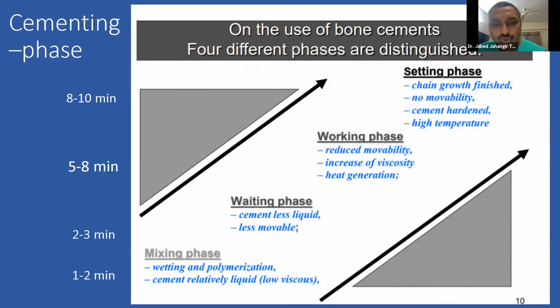We all know it is 4 phases. Mixing phase lasts for 1 to 2 minutes, and waiting phase also 2 to 3 minutes. And what is important is working phase. It's most important. How can we understand clinically when working phase starts? We put some bone cement within a rinsed gloved hand. If it is not hairy, it is no more sticky, then working phase starts, and you just introduce bone cement within the femoral canal or in the acetabulum. The last one is setting. It can vary according to manufacturer, but it is about 8 to 10 minutes.